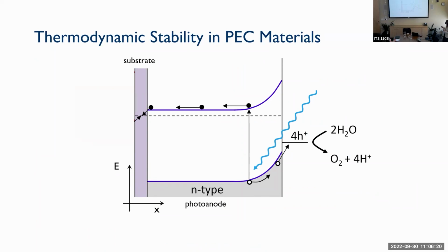And so here I mentioned the conduction and valence band earlier, and upward band bending. So just focusing a little bit more on the ideal process, you shine light and you have charge generation and separation. And ideally, what you have is that the holes that are going to the surface are oxidizing water. However, they can also oxidize the material. And understanding the equilibrium between the two processes becomes very important.